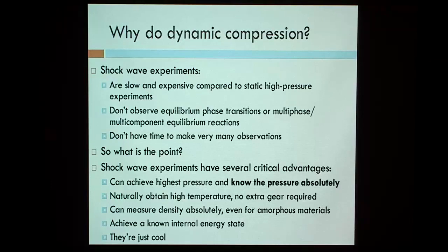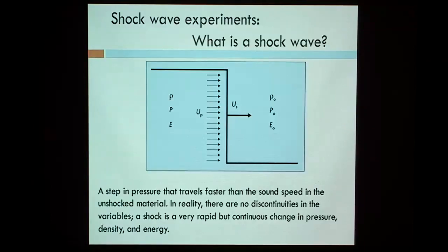Everything you know about calorimetry, measuring energy changes, is all done at one bar. Okay? Because containers in static experiments suck heat out of your sample or put it in, and so you might know the temperature, but you're very unlikely to know the energy. Whereas in a shockwave experiment, we know the energy. Unless we measure it, we don't know the temperature, but we can actually measure both. So it's one of the only ways to get at heat capacity at high pressure. Okay? And, of course, you know, it's fun to blow stuff up in the name of science.